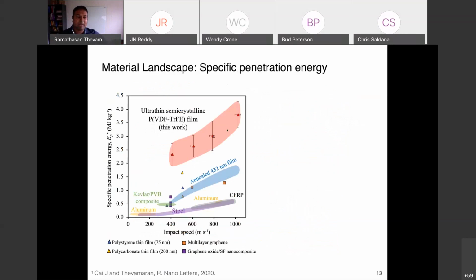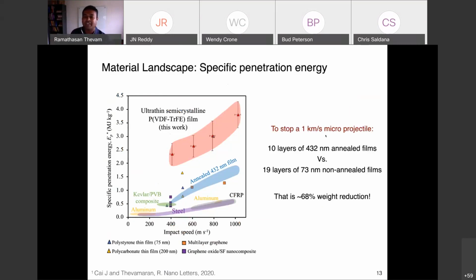If we compare this to other materials, you can see that graphene, which was the best material, is right here, the two squares, and this thinner film dissipates very high energy compared to all of the material systems that have been studied before, both bulk as well as nanoscale materials. So if you want to stop a 1 kilometer per second microprojectile, you would need about 10 layers of this thicker film versus about 19 layers of thinner films to stop the projectile. So you can think of sequentially placing them to create an ambient armor, at a standoff distance from the system you want to protect. And this system would allow you to reduce the weight by about 70% to achieve this very high specific penetration energy.